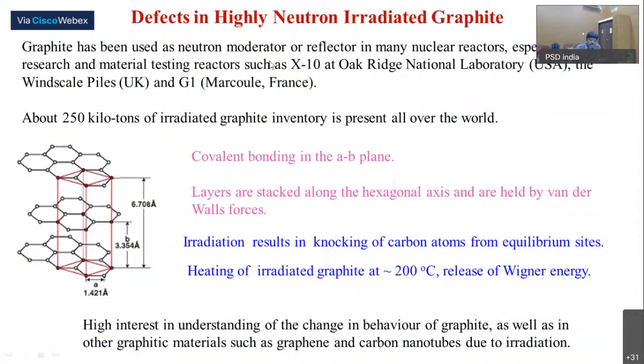As we know, graphite is used as moderator or reflector in many reactors, especially research reactors, and about 250 kilotons of irradiated graphite inventory is present all over the world. This is the crystal structure of graphite. In plane, we have strong covalent bonding, and between the layers we have weak van der Waals bonding. When graphite is subjected to a highly irradiated environment, irradiation knocks atoms off their equilibrium sites, and these atoms sit in between the layers. When we heat this graphite, these interstitial atoms return to their original positions at about 200 degrees centigrade, and this results in a large release of energy, which is known as Wigner energy.